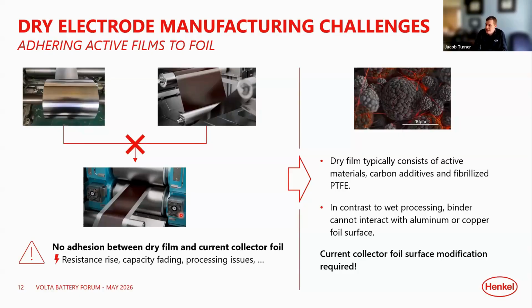So if you just try to adhere these freestanding films to current collectors, they don't really adhere much at all. You can use high temperatures and pressures, and they're not going to stick. You get pretty high resistance rise, capacity fading, and overall processing issues of just the material fully delaminating from itself. So you really need some sort of adhesive layer that is also highly conductive, that has full coverage like a coating would, to get the optimal interface.